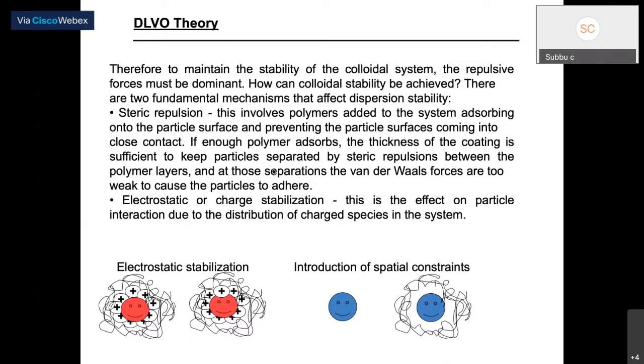Sir, yesterday I prepared a silver nanoparticle, but today it is not stable. What can I do? Actually, I can tell you a method. There are only two options. Instead of doing it in a water medium, you do it in a polymeric medium, adding a little polyethylene glycol or some kind of polymer, then the reaction slows down. Otherwise, you can put in a capping agent, which also controls precipitation. You don't allow the particles to come close, because you're preventing the attraction between them.